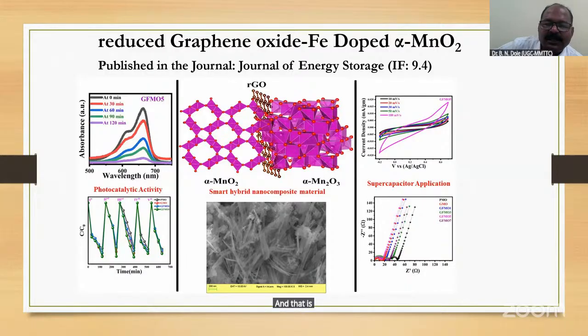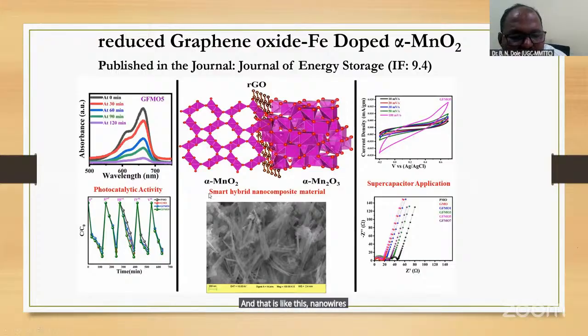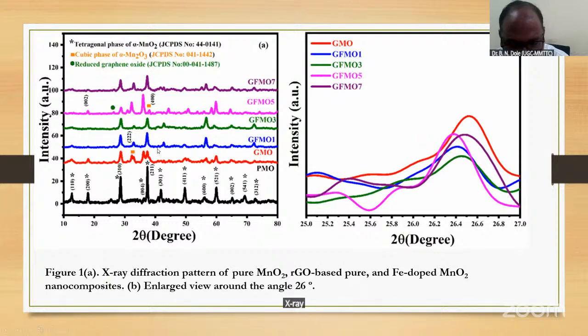And that is the reduced graphene oxide iron doped alpha MnO2, and it is published in the Journal of Energy Storage. And as I said, its impact factor is 9.4. See here the very interesting images we found, and that is like these nanowires. X-ray diffraction peaks of pattern of pure MnO2, RGO based pure and iron doped MnO2 nanocomposites, enlarged around the angle 26.